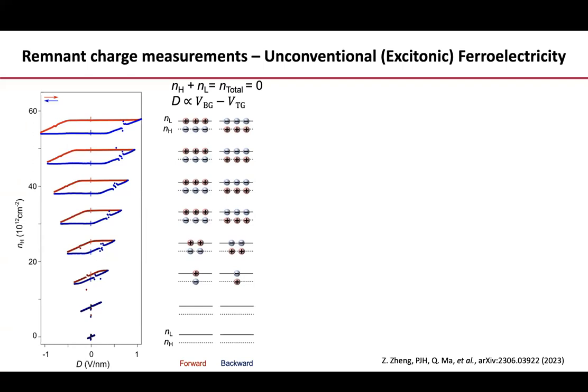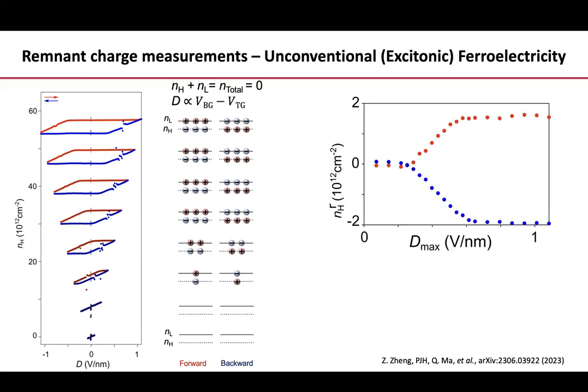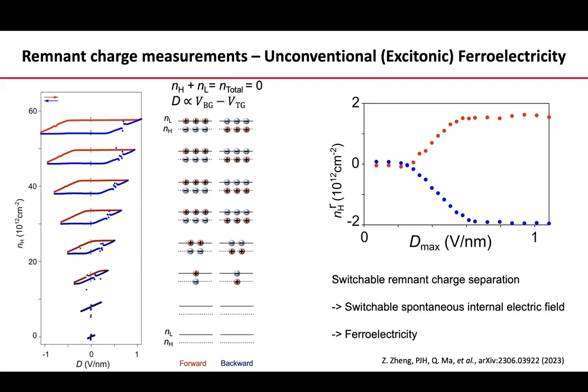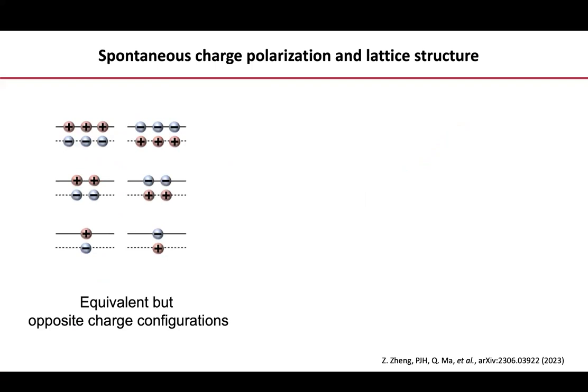Let me just, 1 second, say one thing and then I can get more questions. 5 minutes. Yeah. Okay, so you can measure the remnant hole density, when you go back to zero displacement field. Just remember, in this hysteresis loop, okay, here, when I'm in small displacement fields, I'm just going back to zero. But the moment I start inducing these excitons, the remnant charge when I go back to zero displacement field and zero density varies, okay, depending on how many excitons I have put there, okay? And you can measure, and then it saturates, okay? So one thing that is important is, people tell me like, wait a moment.